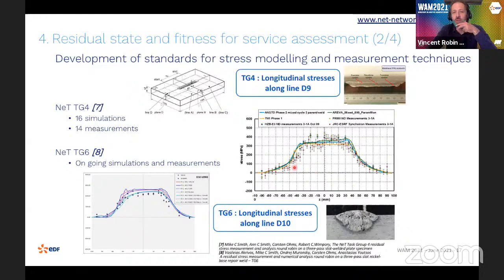Just to give you another view of the amount of data that has been collected. And also, for instance, I can show you here the residual stress through the weld line that has been obtained with different instruments based on neutron diffraction, but also synchrotron measurement. And the results and the comparisons are really, really good between simulation and measurements.